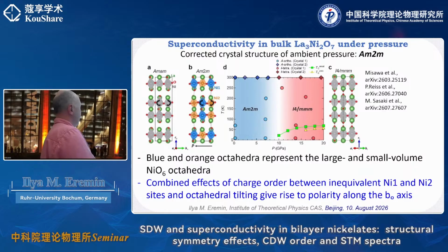So that means that this nickel 1 and nickel 2 have a slightly different charge. And moreover, the Stuttgart group claimed that the transition to this phase already occurs at ambient, around 600 K. So basically everything, magnetism and all the other phases that appear, they appear not in the Amam, but actually at the low symmetry, which is Am2m. And that also gives rise to some polarity along the b axis, which is shown here.